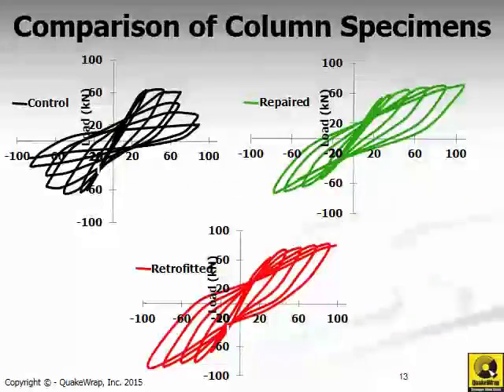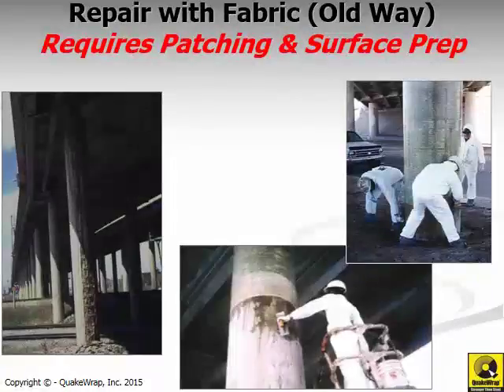So when you put all 3 of these together, we notice that, of course, the old columns shown here in black, those old details are not performing well. But whether we take a damaged column like that and repair it, as shown in green, or we take an older column and without any damage retrofit it, as shown in red, both the green and red graphs are very similar, indicating that the behavior of such columns is severely controlled by and enhanced by the wrapping and confinement that this jacket provides. So this type of system can be used to strengthen columns.